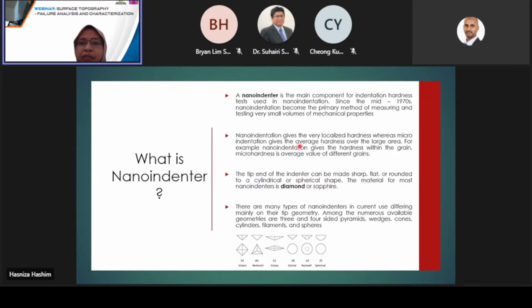Nano indentation will give a very localized hardness, whereas micro indentation gives the average hardness over a large area. For example, nano indentation gives the hardness within the grains, while micro hardness is the average value of different grains. The tip of the indenter can be sharp, flat, or rounded to a cylindrical or spherical shape, and is normally made of diamond or sapphire.